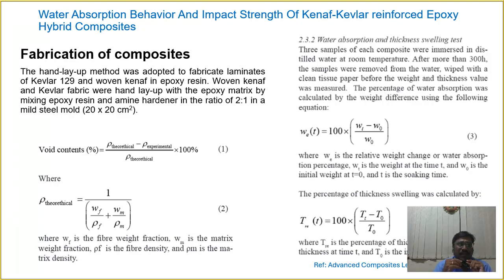So the void content equals rho theoretical minus rho experimental, divided by rho theoretical, times 100%, where rho theoretical is equal to 1 divided by Wf by rho f plus Wm by rho m. It is called a mixture rule, right? Where Wf is the fiber weight fraction and Wm is the matrix weight fraction, and rho f is the fiber density and rho m is the matrix density.